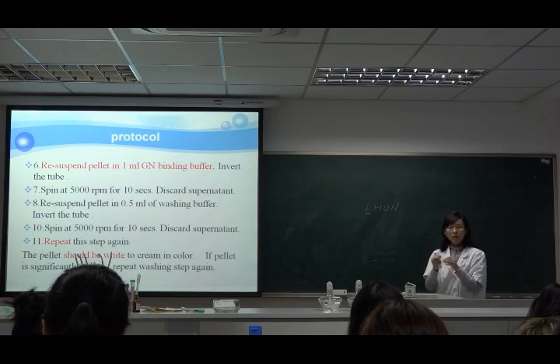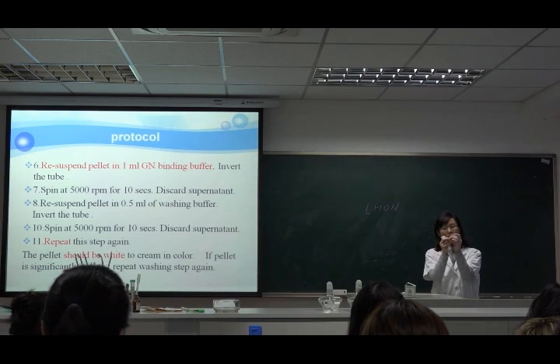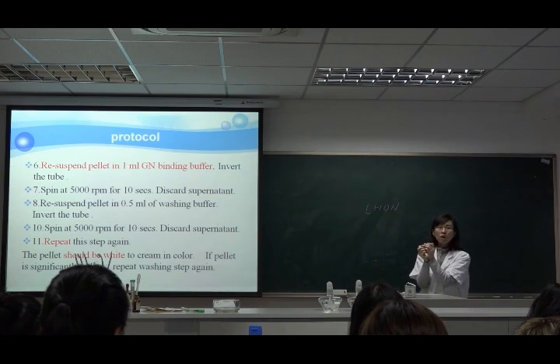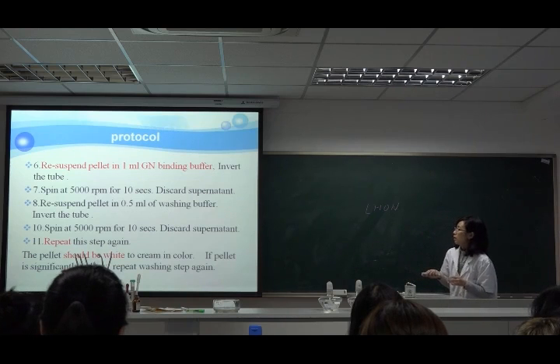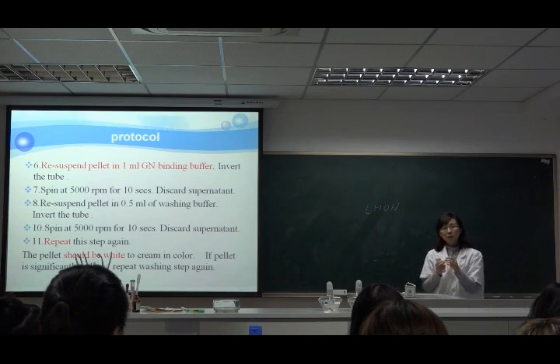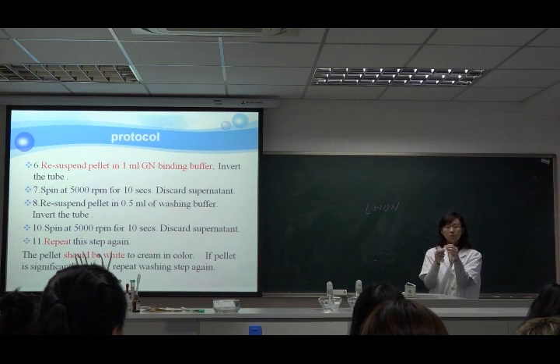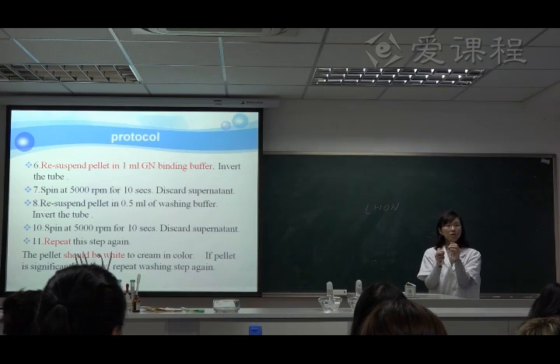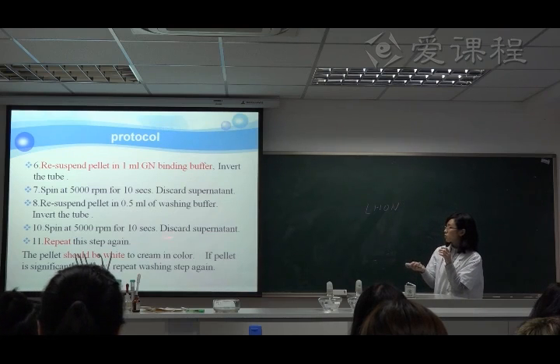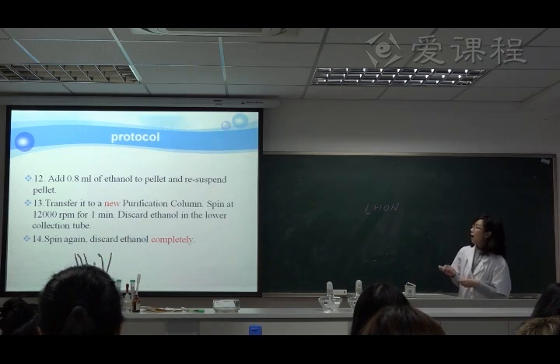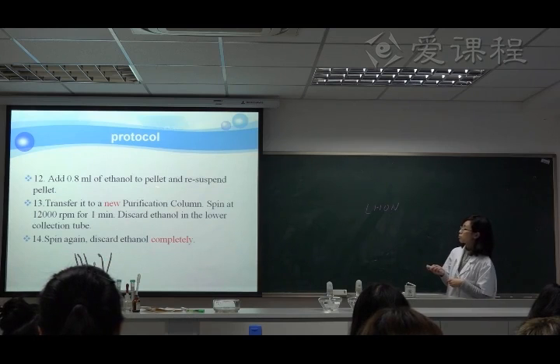And then you can see the color of the pellet. It should be white to cream. If it's white, it's okay, you can do the next step. However, if you see the pellet is still yellow, you should repeat the washing step again. Sometimes when we use blood, you will see the pellet is still yellow. However, when we use cultured cells, it will always be white. So we just need to wash 2 times. It's okay. Then the next step is add 0.8 ml of ethanol to the pellet and resuspend the pellet.